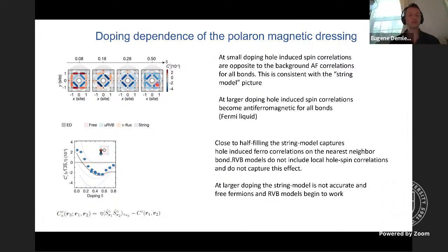And that's something that we expect for the Fermi liquid, because for a Fermi liquid, all there is is the Pauli principle. If we have two fermions, they are much more likely to point in the opposite direction, and therefore, at any distance, we expect to see antiferromagnetic correlations. Here you can again see this change of sign of the three-point correlation function.